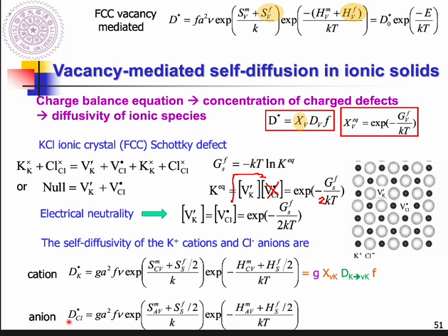Okay, and the diffusivity for chloride is the same idea. Because it is ionic, I put G and x_VCl, the diffusivity f. And here, don't forget, this is x_VK, right? The potassium diffusivity here is this small black ball. If it wants to diffuse, it depends on the fraction of vacancies at the potassium side, and it also makes a jump, right?